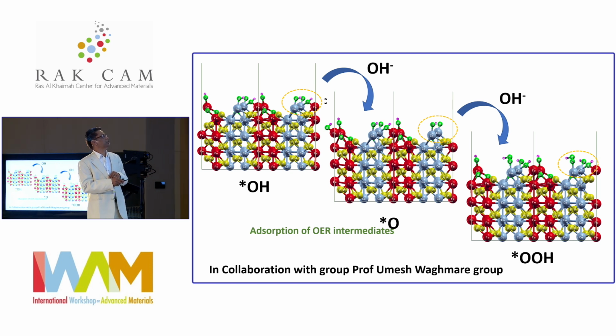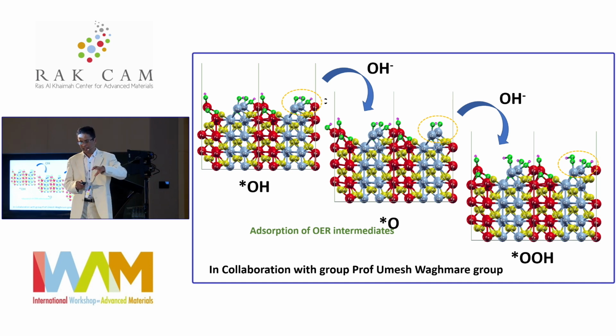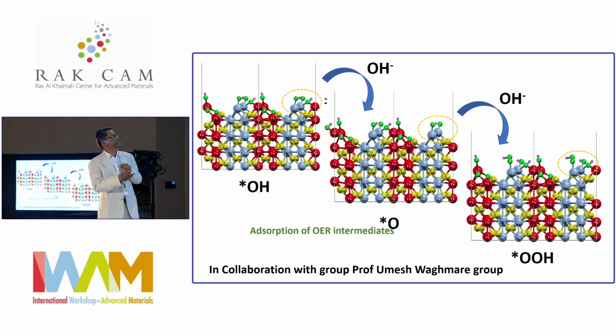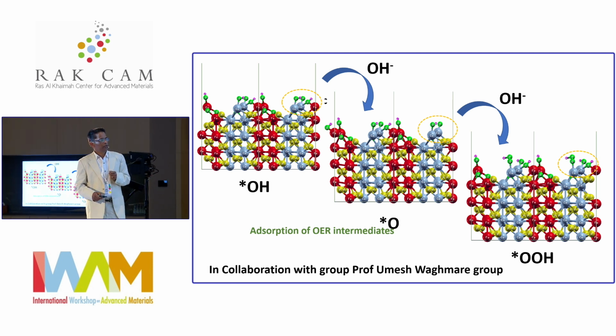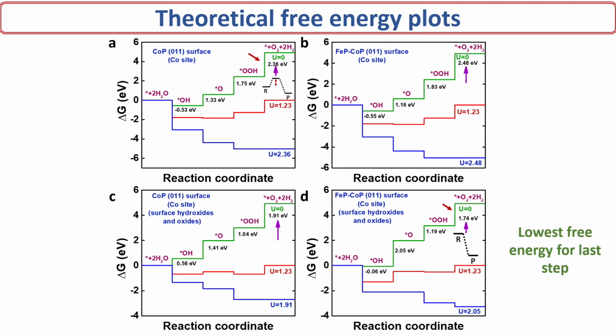The OH prefers to first adsorb on the cobalt, then the iron, though the iron interacts with the cobalt very strongly; once adsorbed, it won't go out. So the first preference is that the OH goes to the Co sites, then hydrogen is removed from that OH, followed by addition of OH to form COOH, and this further releases the oxygen. If you look at the energetics, compared to cobalt phosphide or iron phosphide, this mixed one at the 011 surface shows the lowest free energy of adsorption, a very fast-moving step kinetically. Compared to any other steps, the OOH to O2 step here is very low in energy, so it is favorable for this fast reaction at the interface.